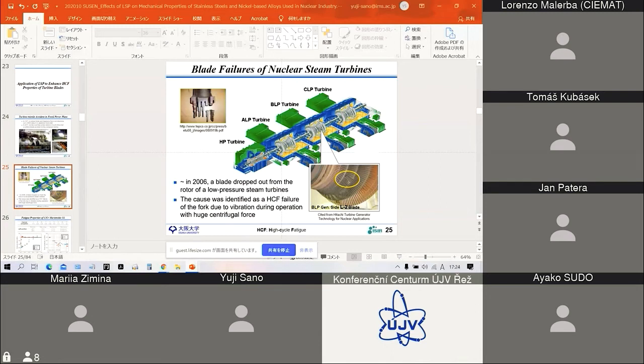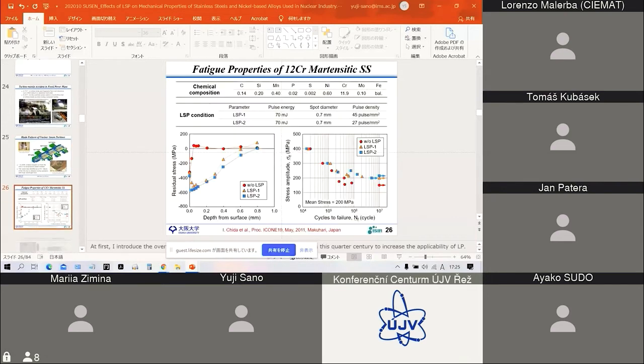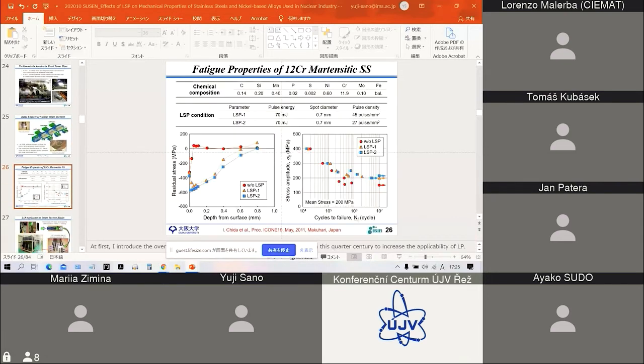So you can see the long turbine blade dropped off from here, from the turbine rotor. The cause was identified as a high cycle fatigue failure of the fork due to vibration during operation with huge centrifugal force. So at first we did the experiment of LSP to confirm the effect on the residual stress, and then did the fatigue testing like this. Anyway, the result was successful, encouraging.